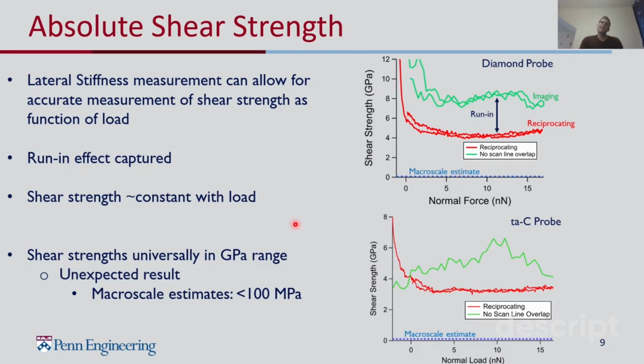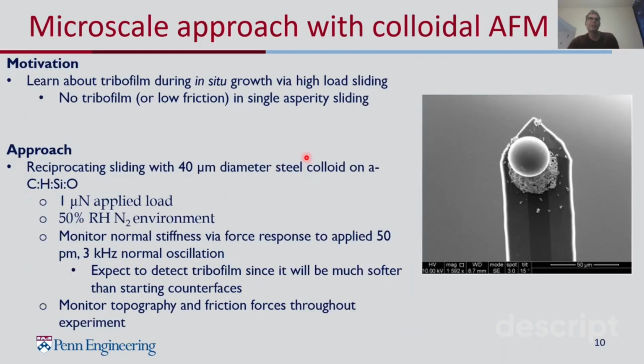And so one hypothesis you might have about what's driving the difference is the tribofilm, given that in these nanoscale experiments, we typically did not see any evidence of tribofilm growth. And so we really are interested in what the effect of the tribofilm may be, given that we don't see lubricity really in the absence of the tribofilm. To get at that, we switched to a different length scale. So we moved to the microscale now, where we can have a multi-asperity contact, where maybe different phenomena will occur.